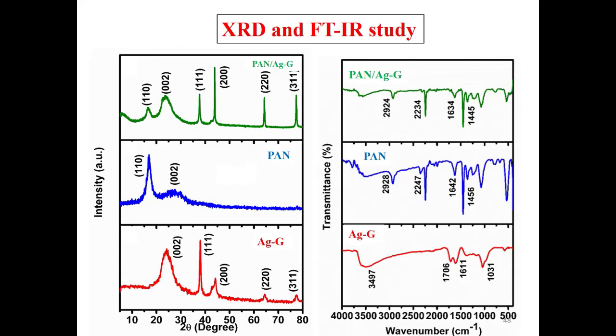Characterization of these fibers by XRD and FT-IR study shows the formation of uniform-size nanofibers, with the presence of crystal planes and functional groups, showing that the PAN-Ag nanofibers are uniformly and effectively synthesized.